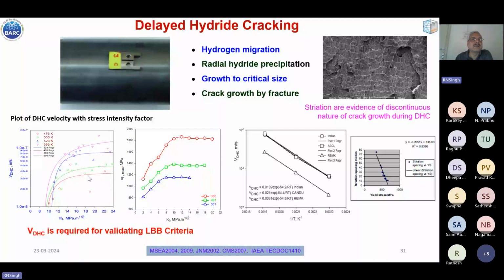These four curves are obtained at different temperatures. At lower temperature, we have got lower DHC velocity, and as the temperature is increased, plateau DHC velocity also increases. Now, why during this plateau regime is this DHC velocity independent of the stress intensity factor? For that, we did some calculation.